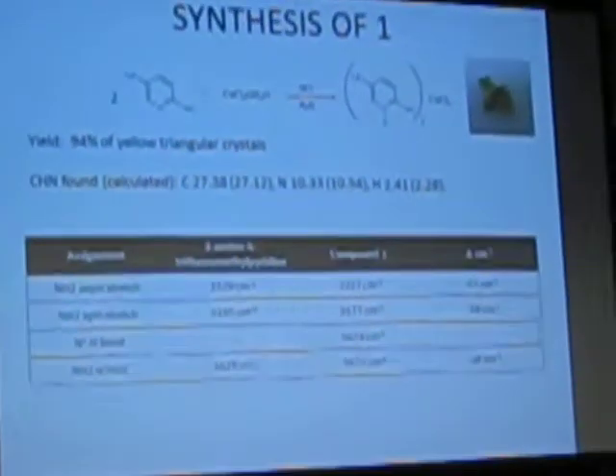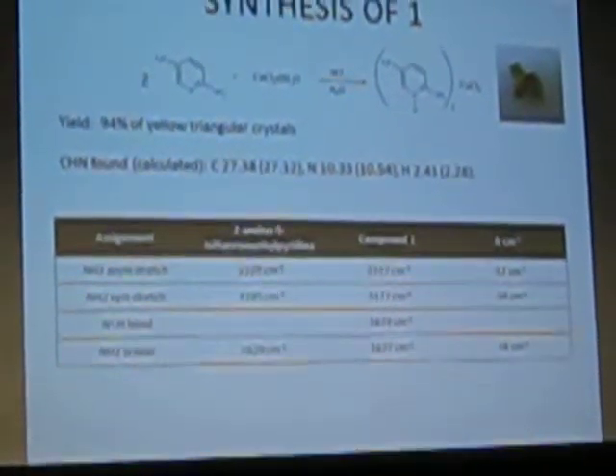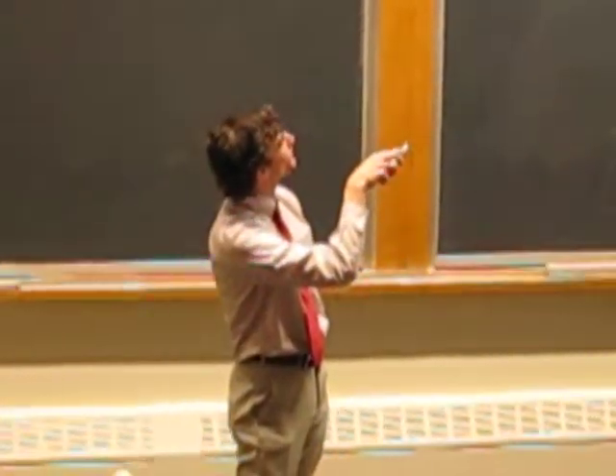it's a very simple reaction scheme. You react a pyridine compound in a 2-to-1 ratio with the metal halide in an aqueous solution with a little bit of acid, and you create this over a slow evaporation of the solution. After a couple of weeks, you get these beautiful crystals.